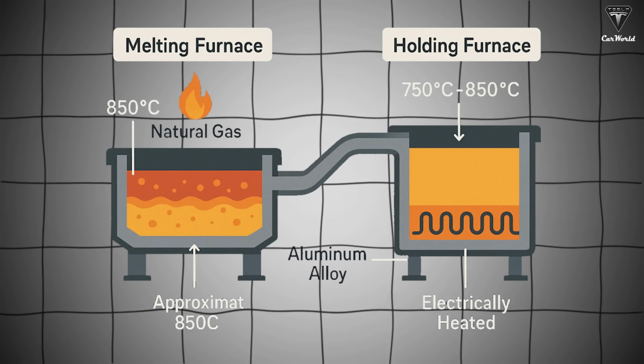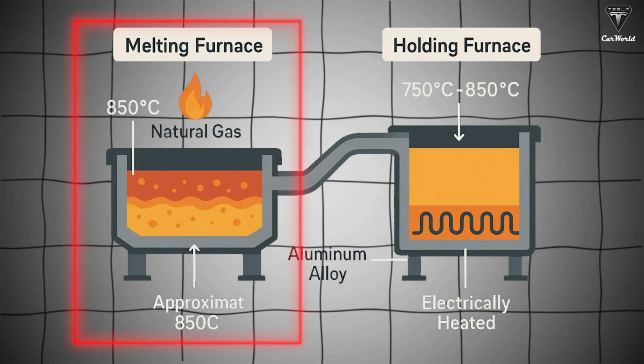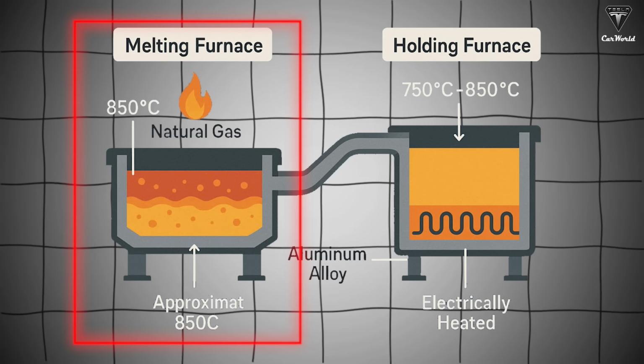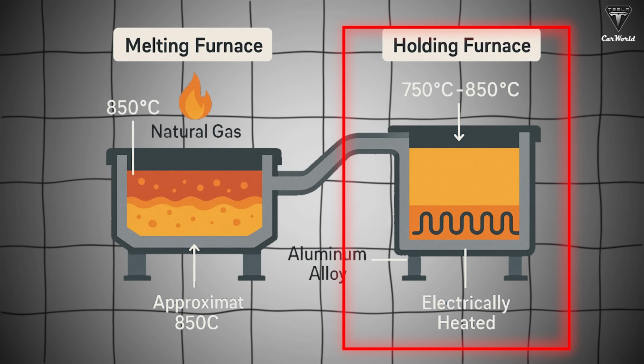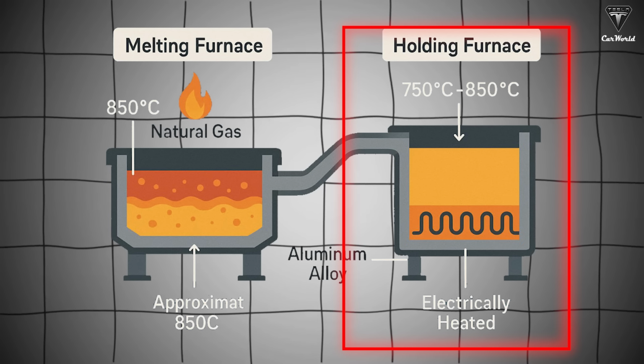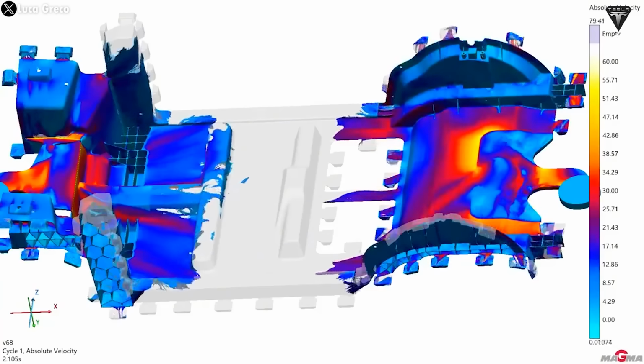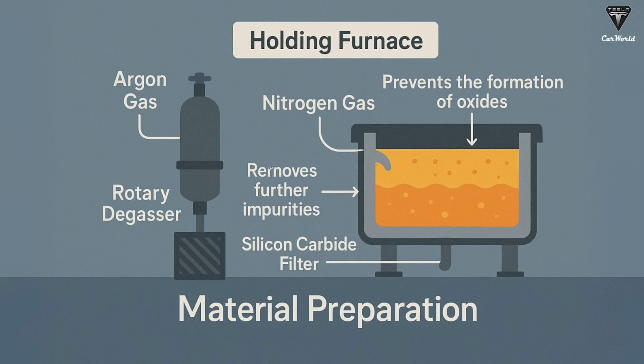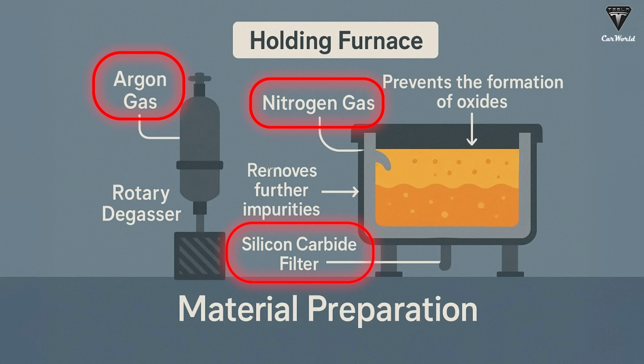The new GIGA Press system uses a dual furnace setup: natural gas for the initial melting furnace and electricity for the holding furnace, allowing for precise temperature control with no smoke or dust, resulting in denser aluminum and a stronger structure. The empty space inside the holding furnace is filled with nitrogen to prevent oxidation. At the same time, technicians use argon gas, rotary degassing equipment, and silicon carbide filters to remove impurities and particles larger than 25 microns, ensuring the highest possible metal purity.